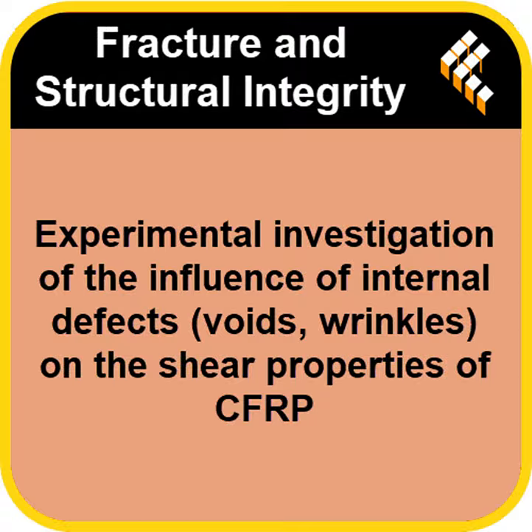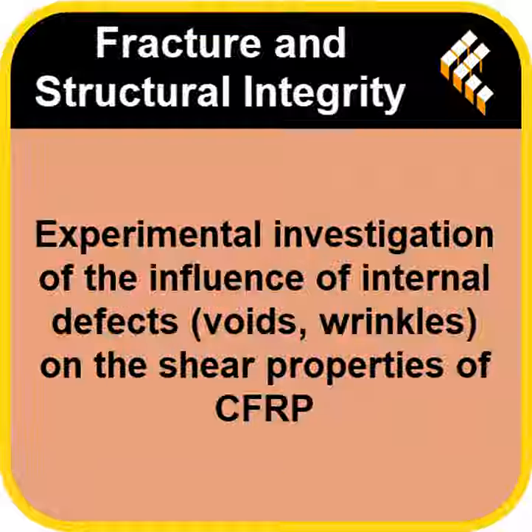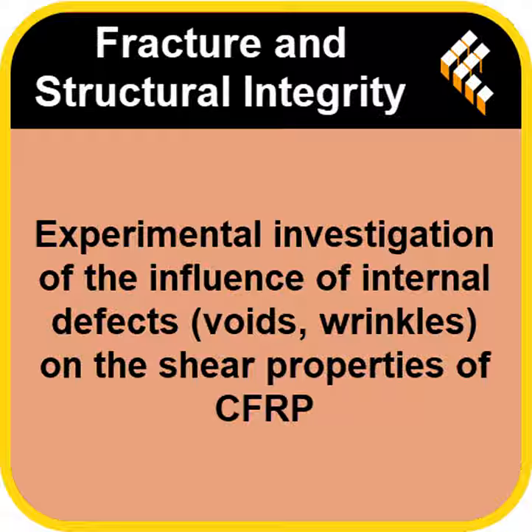It really changes how you might think about NDT results, doesn't it? It does. Maybe the focus should be less on the exact morphology of a detected void and more on accurately quantifying its overall size or volume fraction, at least for shear critical parts. So prioritize measuring the how much over the what shape? Sort of, yeah. And another positive point, despite the defects, all the samples, voided or not, failed in the expected way, vertical shear cracks in the gauge section. The test itself was consistent.